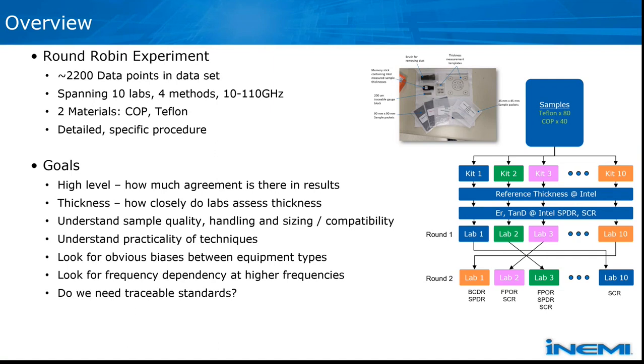They were measured at Intel for a reference thickness and also for dielectric constant loss and loss tangent using the equipment sets that we had available at Intel. They were then routed to the different labs, and each lab measured the samples in their kit according to the techniques that they had available in each of the labs. Those kits were then rerouted to a different set of labs, and by doing this, we tried to get as much coverage as possible for each individual sample in the kit, spanning the different methodologies available to us in the different labs. And so there isn't perfect overlap, but there was a lot of overlap for the different samples.